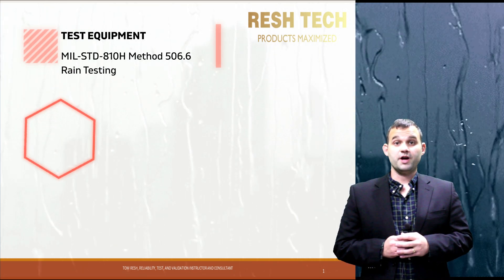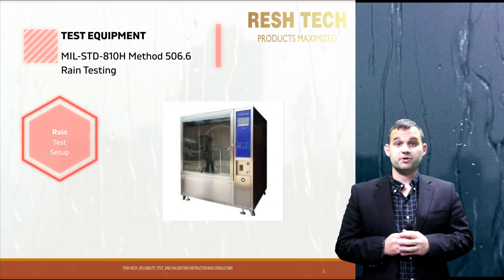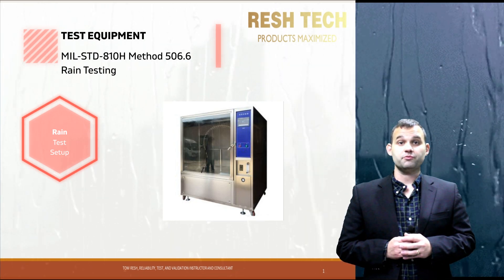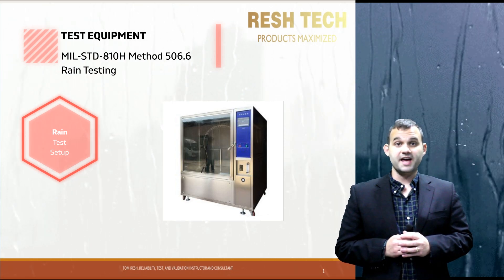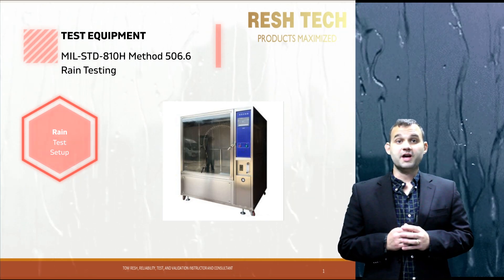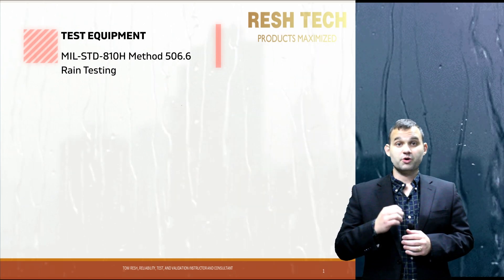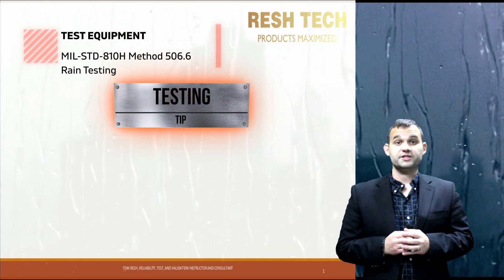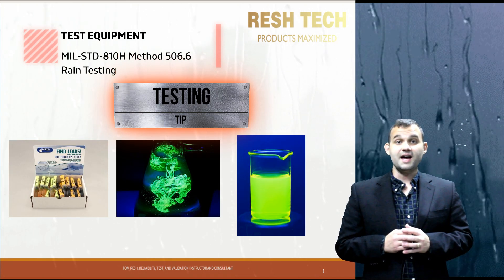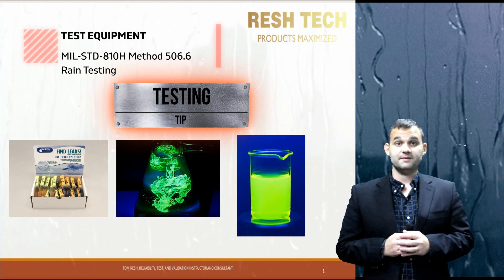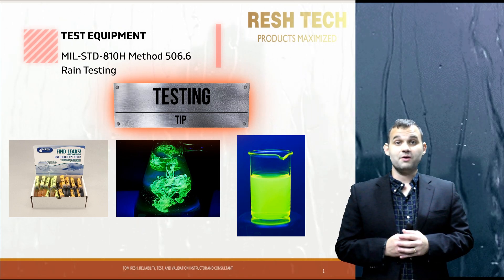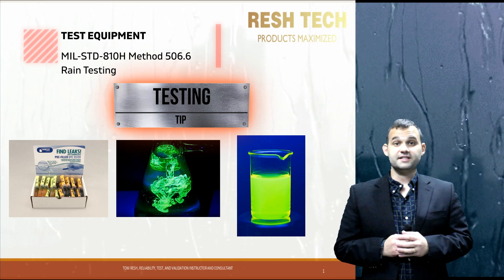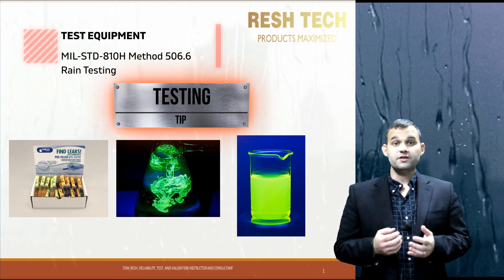The first is rain. This uses a rain chamber with spray nozzles to provide the desired amount of simulated rainfall at a specified rain droplet diameter and velocity. Pro tip: a great way to get a jump on failure analysis is to include a fluorescein dye in the water source when performing rain testing. The fluorescein dye will allow you to see leak traces and leak paths inside your system and where the fault occurred.